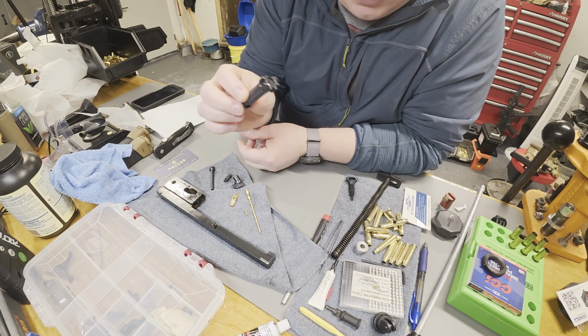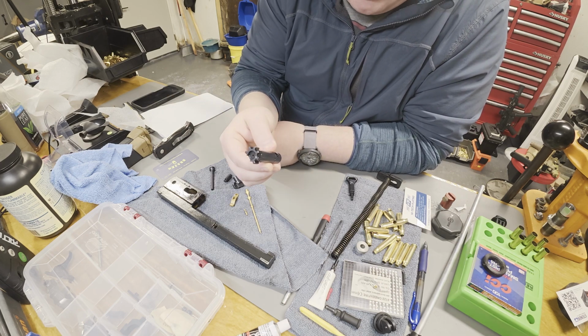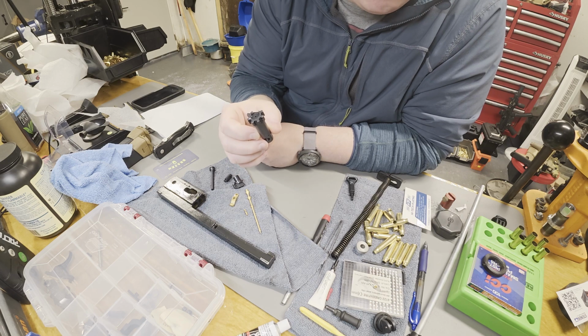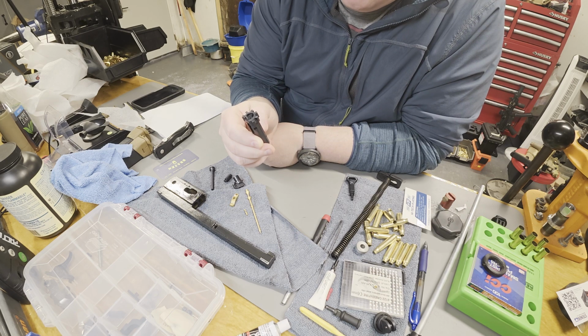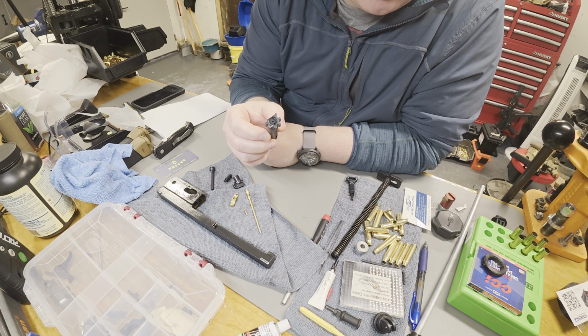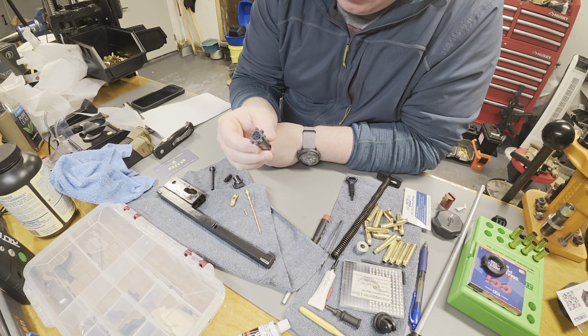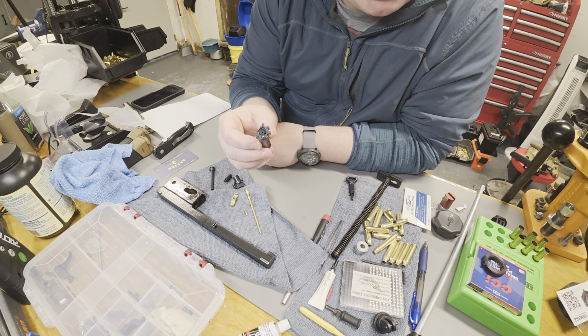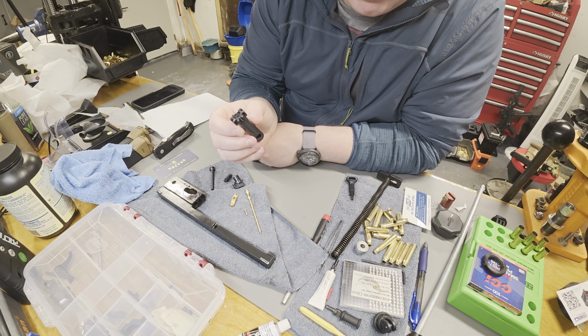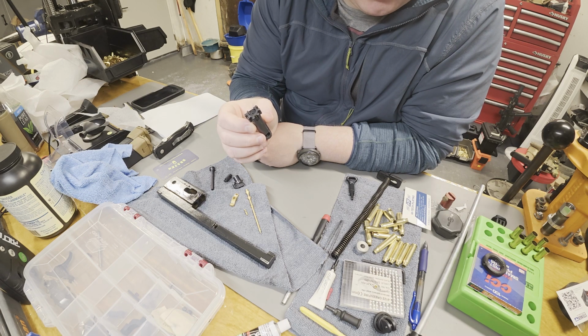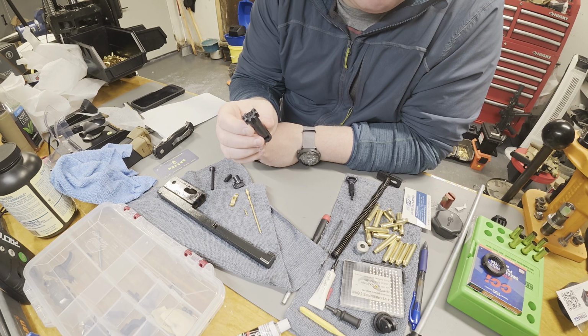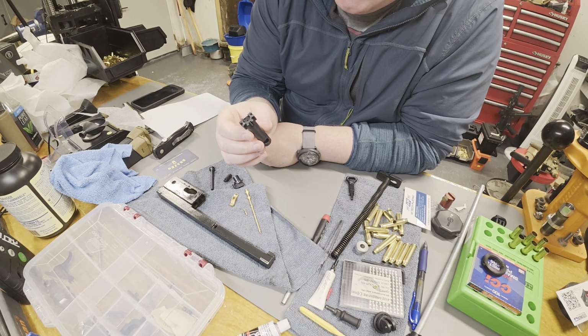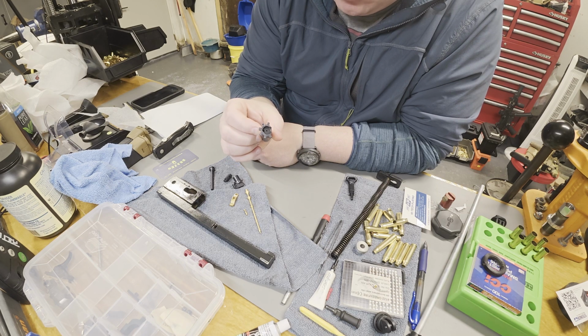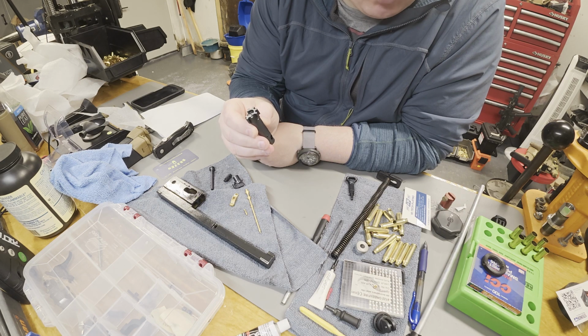However, the AlTiN has very good heat resistance. It has very good shock resistance. It has good coefficients of friction. It's not close to DLC, but it's way better than bare steel. It's way better than black oxide, and I believe it's on par or slightly better than salt bath.